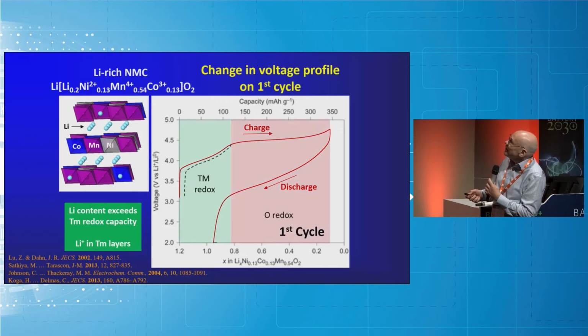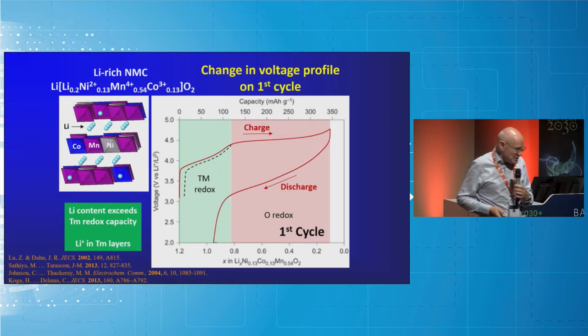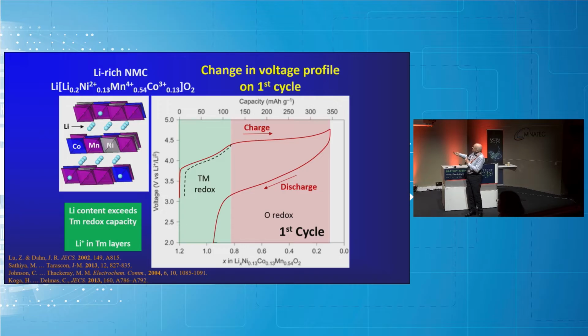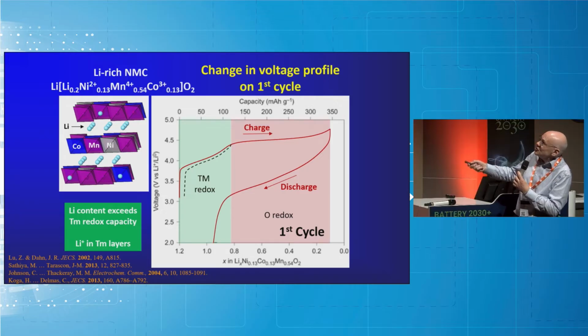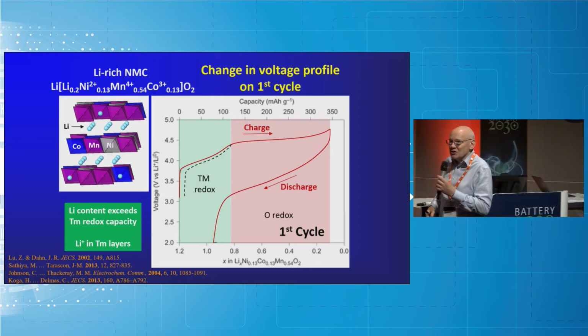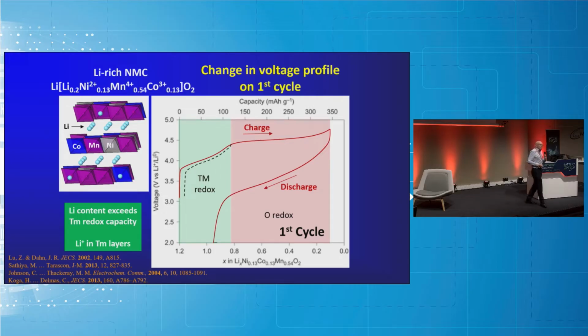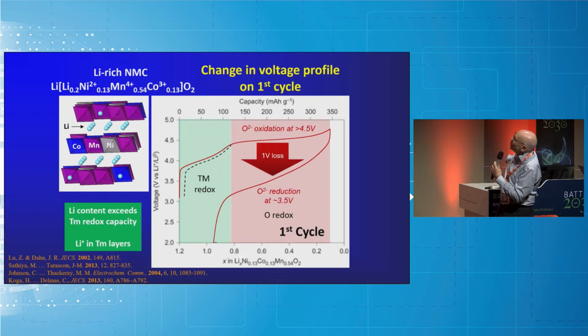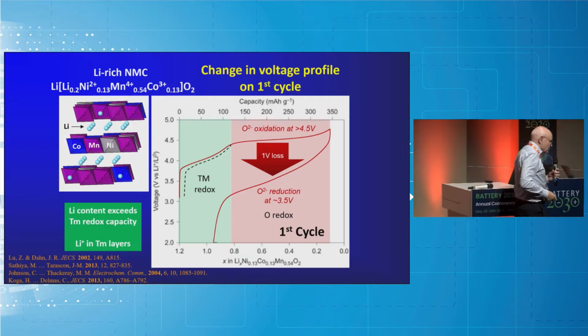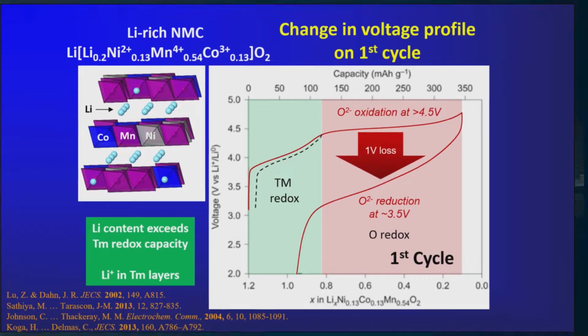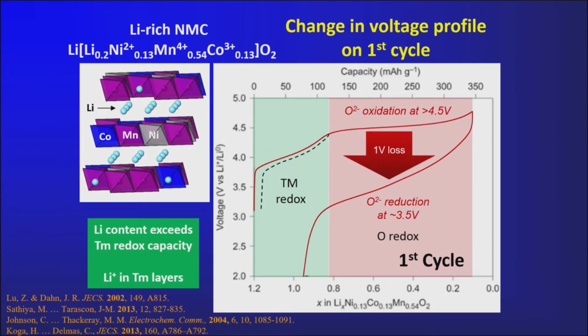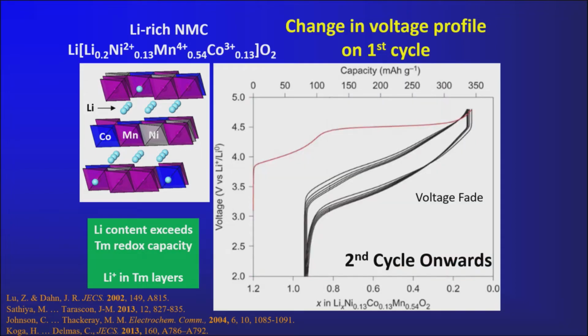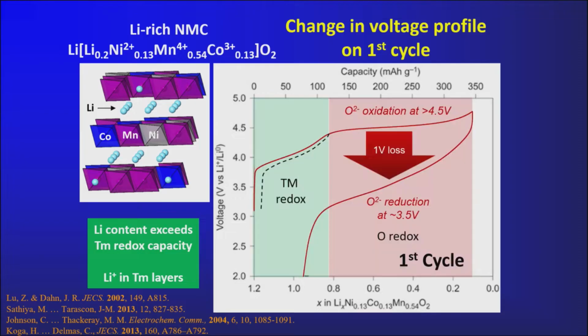Because if you simply cycle back and forth in this region, so this is the load curve, charge, discharge of one of these materials, made a cathode in a cell with a lithium anode as a reference, and there's the charge and the discharge. And if you stick in this green region, which is the transition metal redox region, so you're only oxidizing and reducing the transition metals, then everything is nice and reversible as usual. But as soon as you go further than that and start stripping electrons from the oxide ions, all hell breaks loose. When you come back down this way, you come back down at 1 volt lower in energy, so you've lost the amount of energy you can store. You really want to go back and forth along this plateau, but you have to come down here on discharge. You can cycle it thereafter like this, but you've certainly lost that energy, and there's still significant hysteresis here, as you can see.